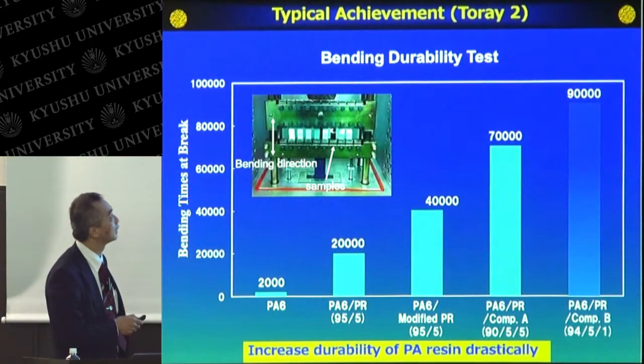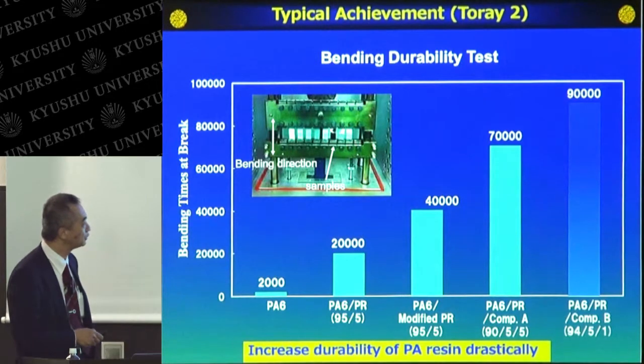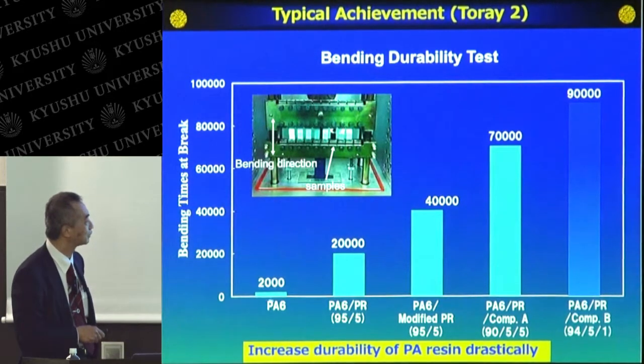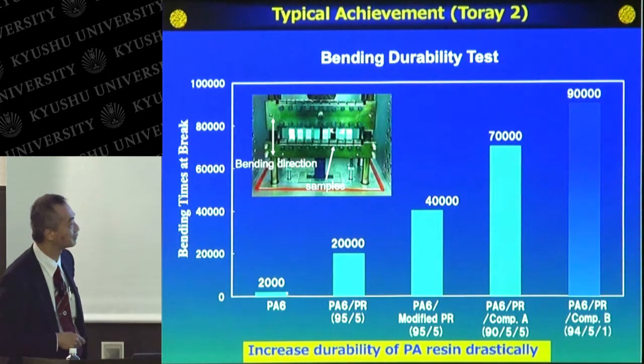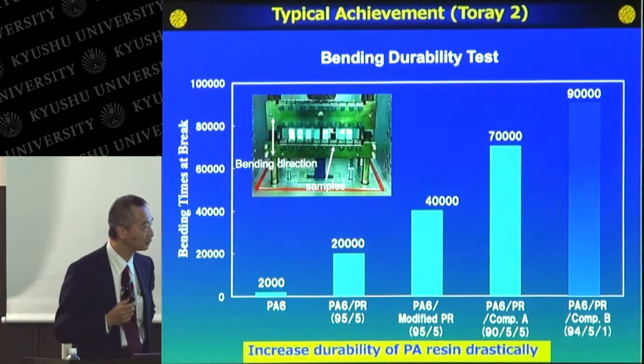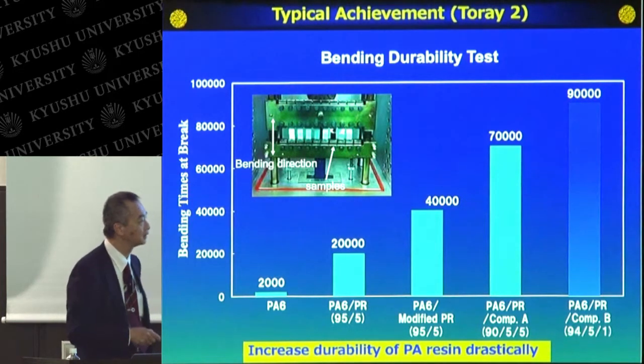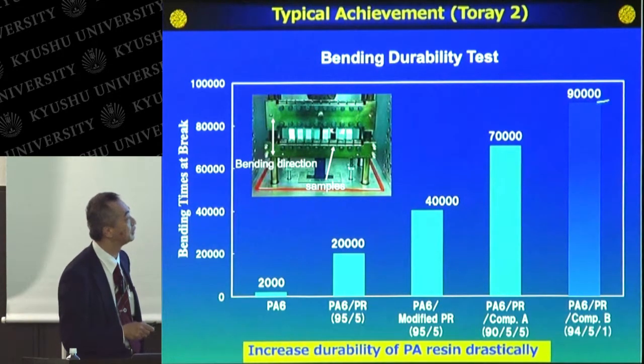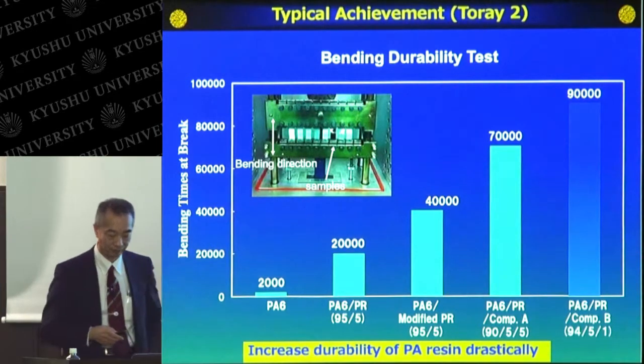And this shows the bending durability test. Usual polyamide resin breaks at about 2,000 bending times, but when only about 5% of polyrotaxane is incorporated in the polyamide resin and cross-linked, the durability is drastically improved, about 45 times like this. Okay.